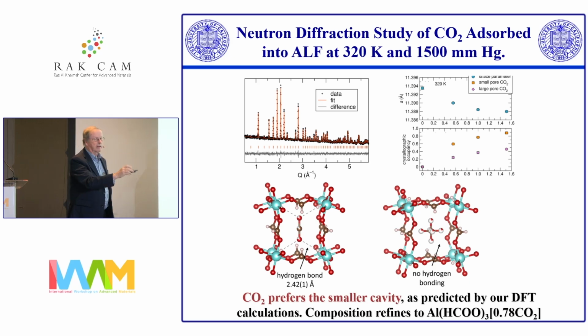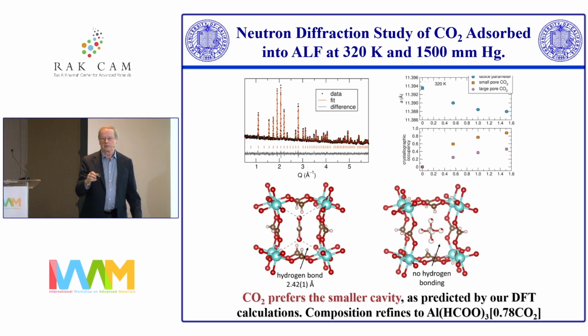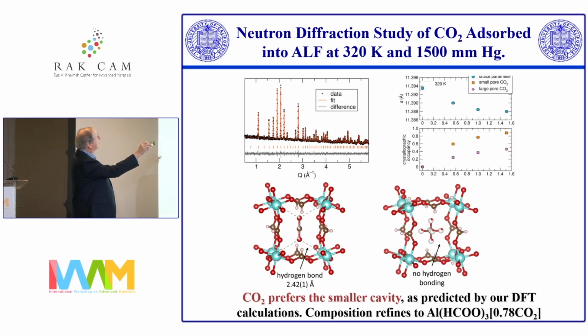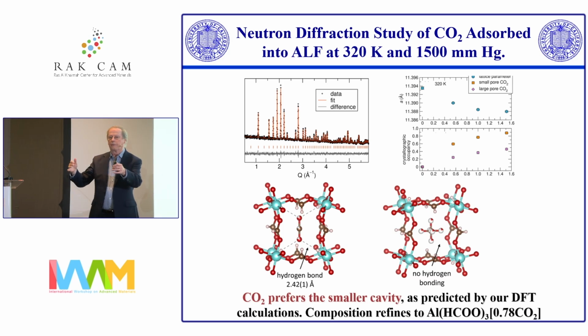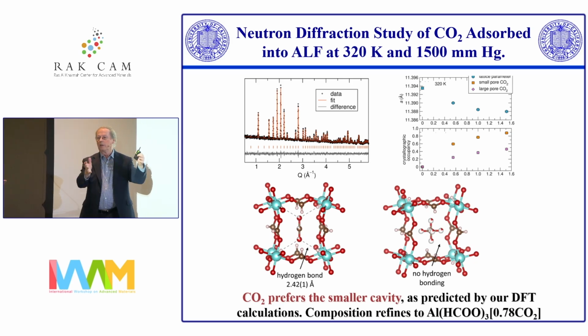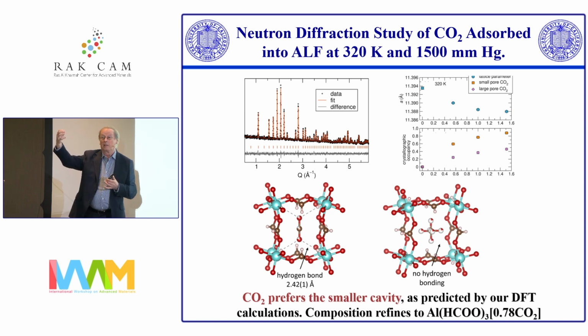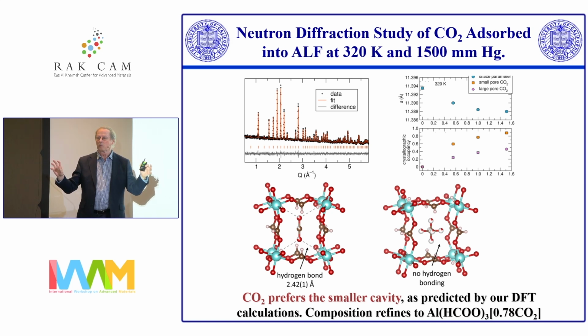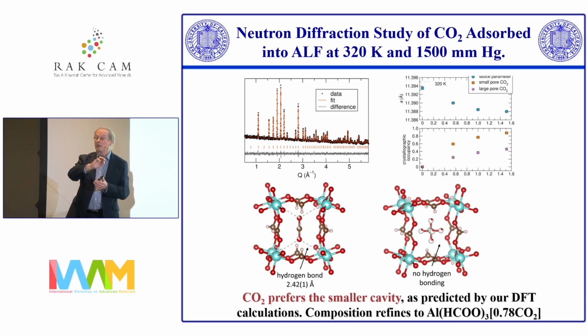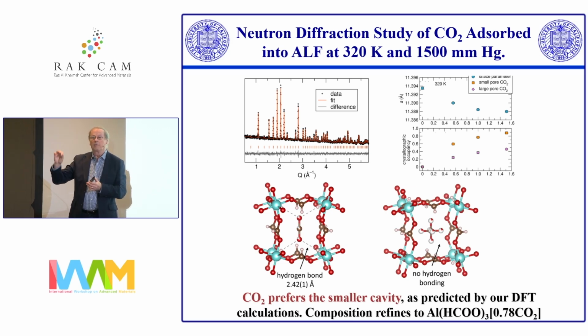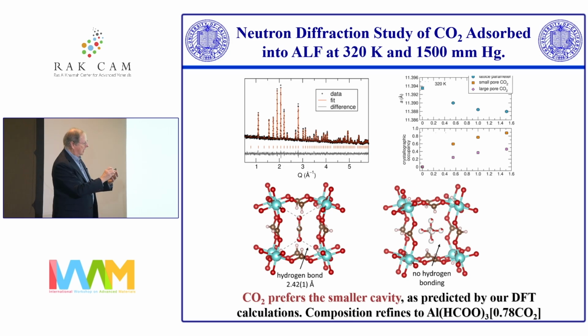And I've worked on the Rietveld method for about 50 years. This is as good as it gets. And so what we did was to do the neutron diffraction as a function of loading the CO2 into the system. And so you can see the CO2 going in because it appears in the structures. And there are two types of cavity here, not just one, actually. And you can see the CO2 going into both of the cavities as you load it up.